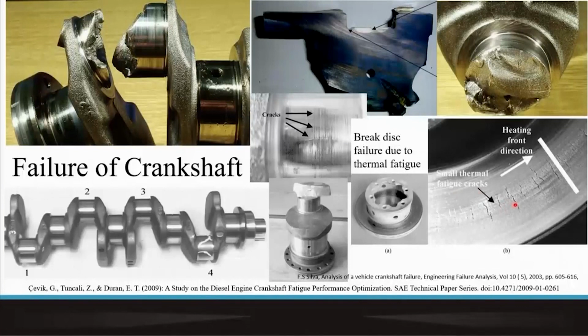In all these examples, this is a different kind of crack. This happens because of thermal fatigue. This is a brake disk, and this is a curved surface, please remember, and these cracks are completely perpendicular or normal to the curvature. These cracks develop when material tends to flow more than its elastic and plastic limit, and eventually that amount of deformation cannot be supported anymore, and the total amount of energy input is higher than the fracture toughness of the material, then such cracks develop. But this is not yet catastrophic because these are hairline cracks which have developed, but unless they are arrested and repaired, it might lead to a complete catastrophic failure.